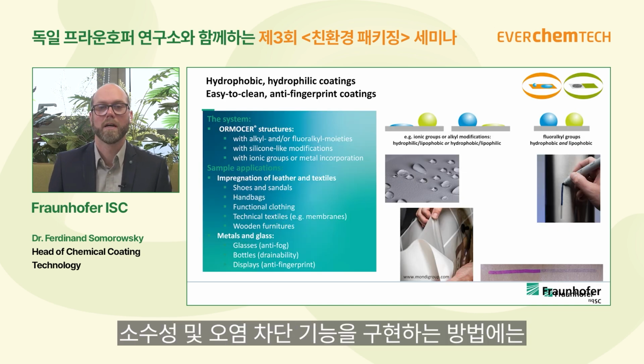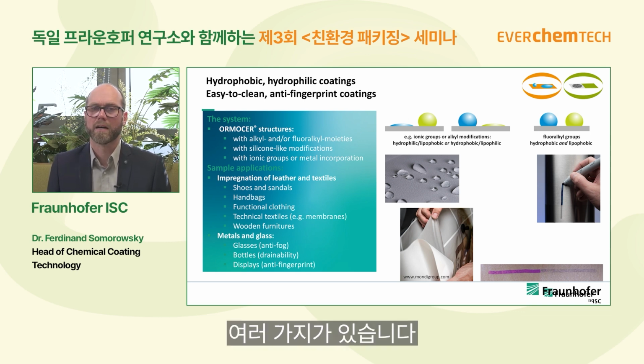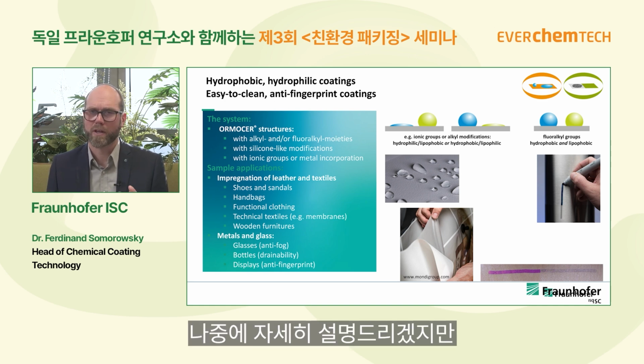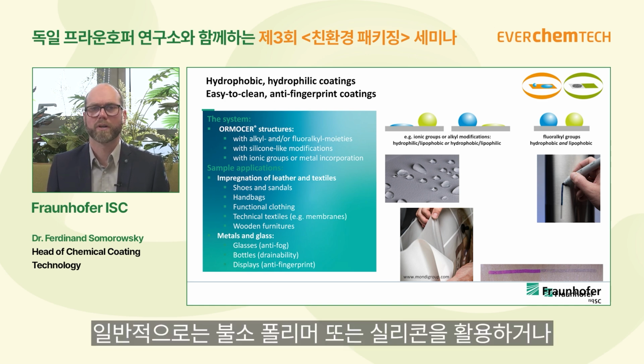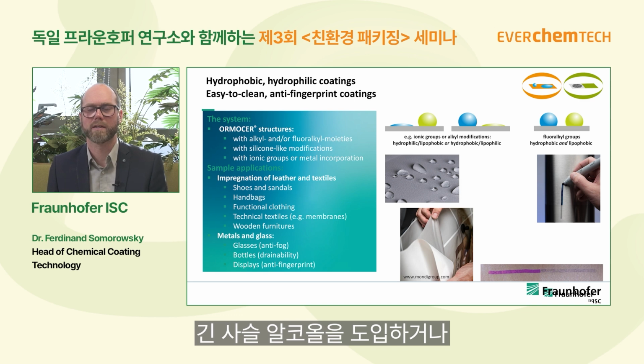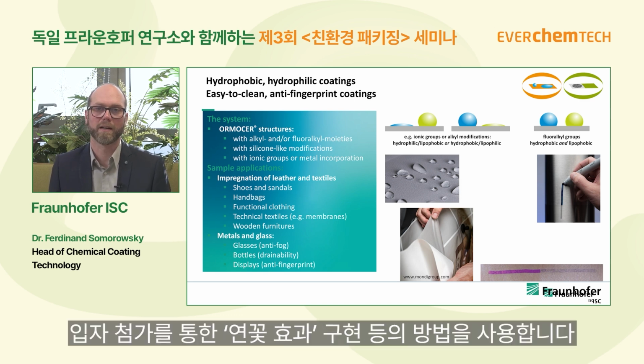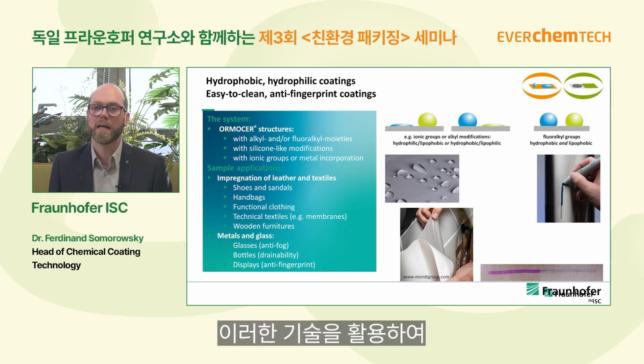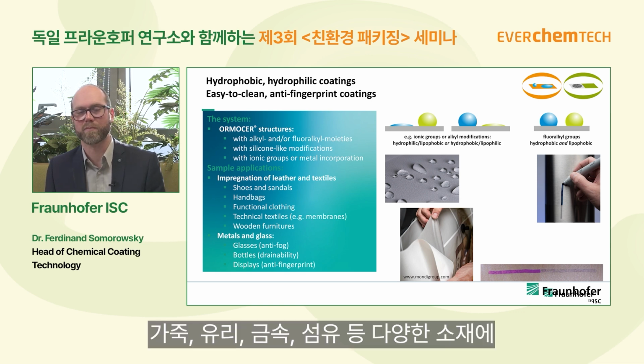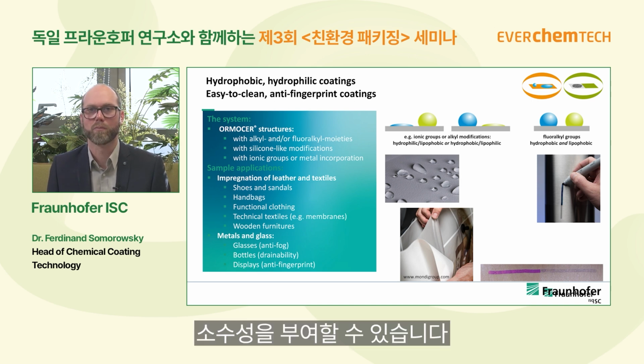When we look at this easy-to-clean, hydrophobic behavior, we can address this by different approaches. I come to that point in detail later, but you can use, for example, fluoropolymers, silicones, long alkyl chains. You can add particles to have the classical lotus effect and equip different materials, starting from leather, from glass, from metal, textile, and produce a water repellent property here.